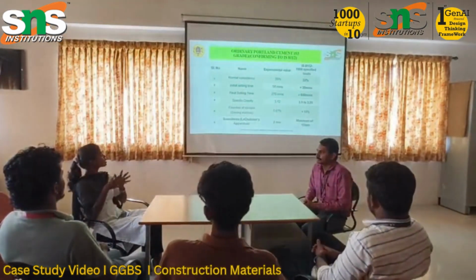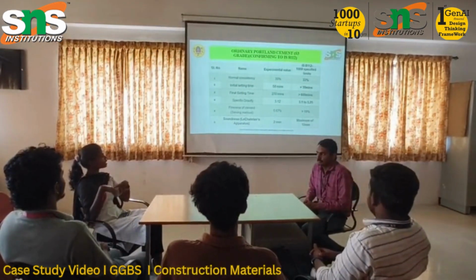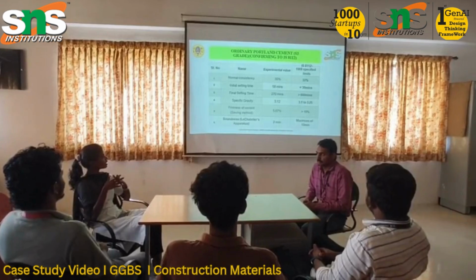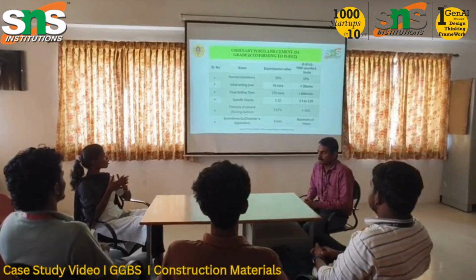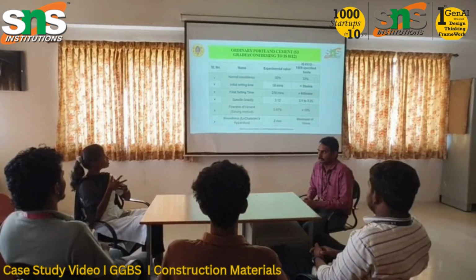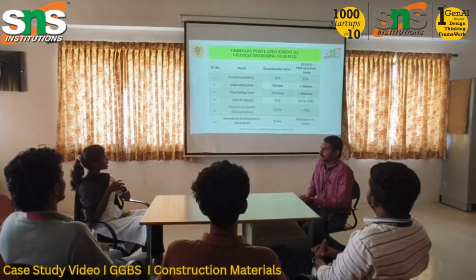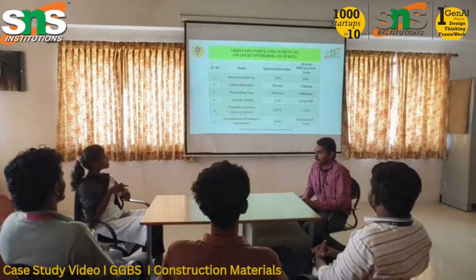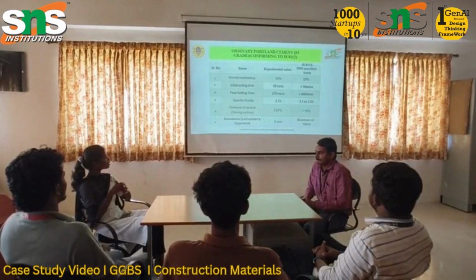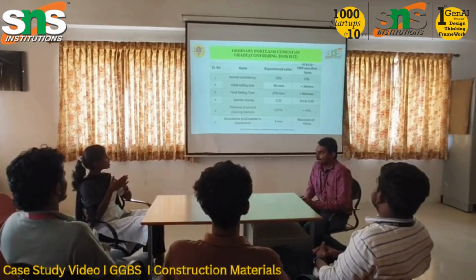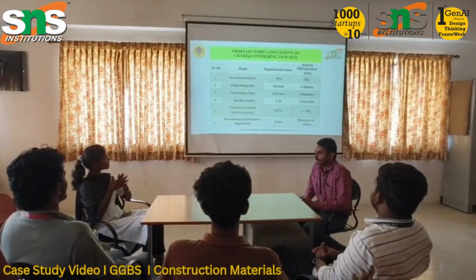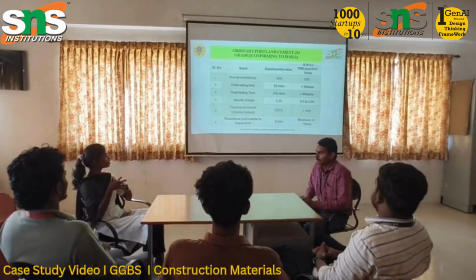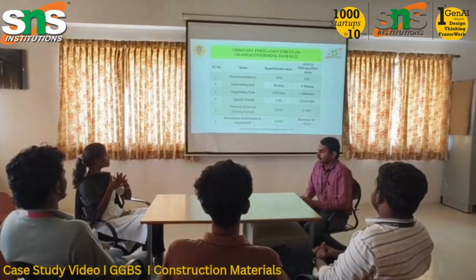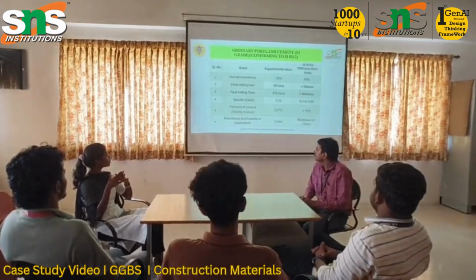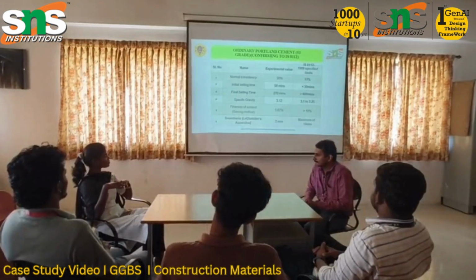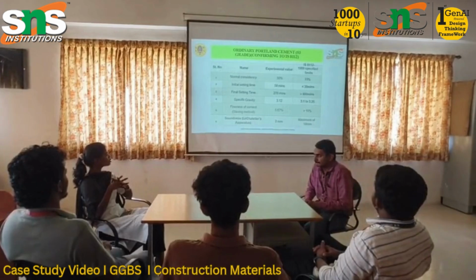Normal consistency as per IS 8112:1989, the specified limit is 33%. For normal consistency, we got 30%. Next, the initial setting time we got is 58 minutes, and the final setting time we got is 270 minutes. The specific gravity is 3.12, and the limit is 3.12 to 3.25, so it is within the limit. The fineness is 5.67%. The soundness we got is 2 mm.